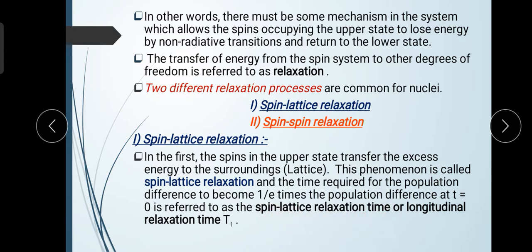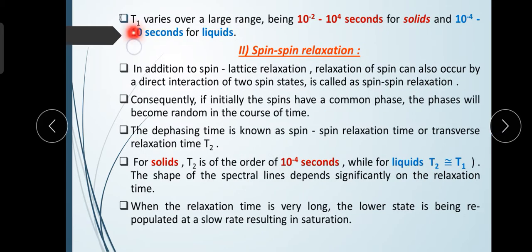So this is the spin lattice relaxation, but the value of the spin lattice relaxation time is different for different materials. T1 varies over a large range, being 10 to the power minus 2 to 10 to the power 4 seconds for solids and 10 to the power minus 4 to 10 seconds for liquids. That means the spin lattice relaxation time is different for solids and liquids. So this is the spin lattice relaxation, through which the energy gets transferred to the lattice.